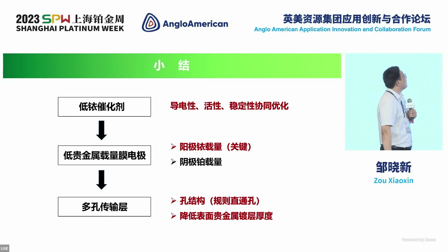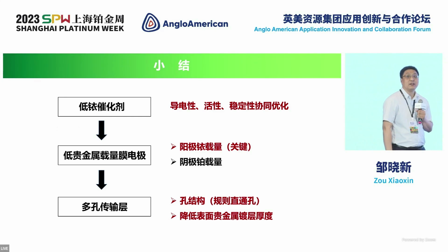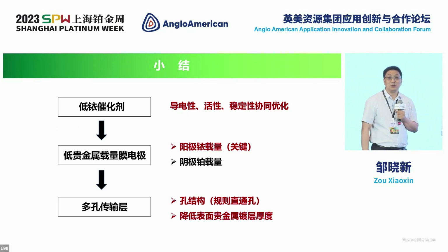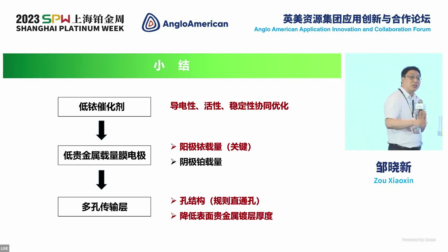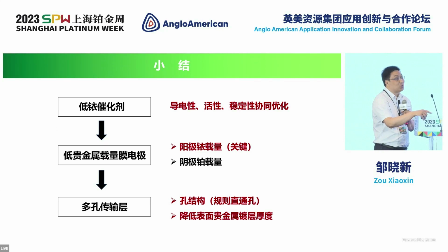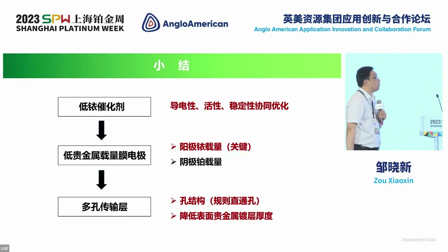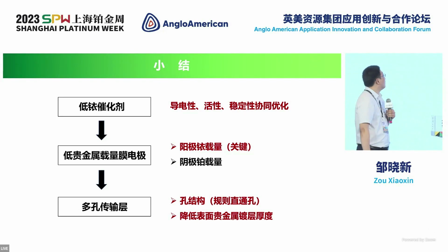A few words in summary regarding the anode catalyst. There are several things we can do. We need to have the synergy of conductivity, activity, and stability. Why I'm putting conductivity in the very first place is because in catalyst there is the triangle of stability, activity, and selectivity. However, if you want to develop low iridium catalyst, conductivity is our first consideration, without which we don't actually need to consider any other factors because they're just not relevant.